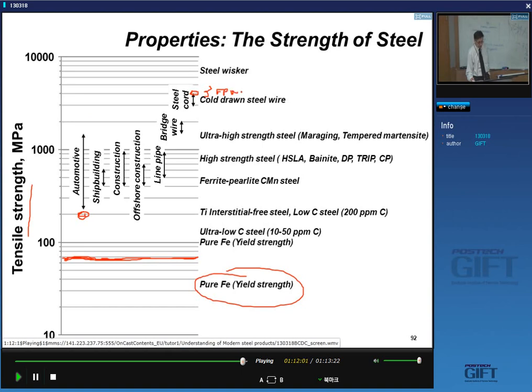Okay? And these are materials that are not exceptional. You can just go ahead and buy this material. Yes? You can buy many tons of it. I'm not talking about exceptional materials here. So you basically have alloys which go from very soft in tensile strength to very hard. And the amount of alloying we use is actually minimal, right? I can tell you that the softest material has close to 1.5% of alloying elements, and the cold drawn has maybe a little bit over 2% of alloying elements. Am I saying this right? Yeah, less than 3%. So it's amazing what a range of mechanical properties you can achieve with virtually a pure iron matrix, close to a pure iron matrix.